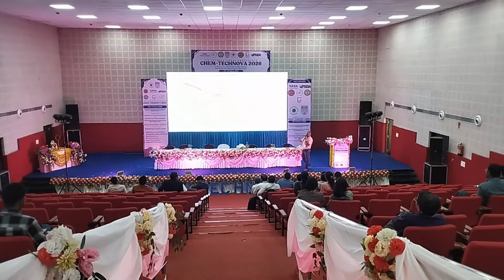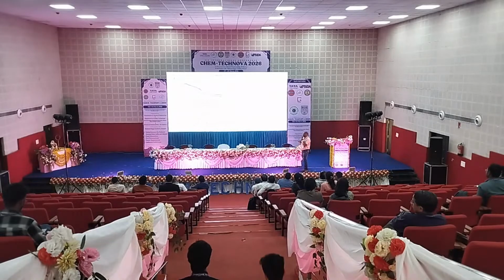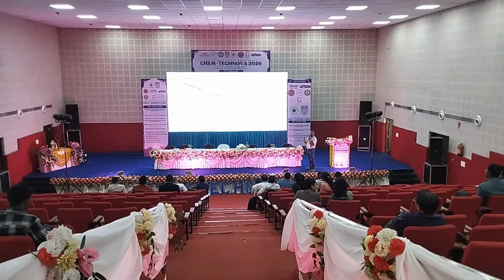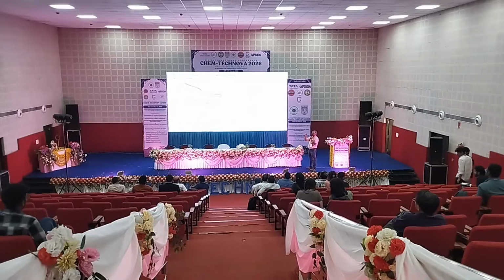And in this thermogravimetric analysis, you apply temperature from room temperature to 1000 degrees centigrade, and I wanted to see how the mass loss is happening within the material. It has two phases. One is the resin degrading, the other is the filler starting to degrade. When it is more than 50%, whatever temperature you apply, 50% of the material is getting retained. It is not thermally degraded. That means we know that this is a thermally stable ablative material.